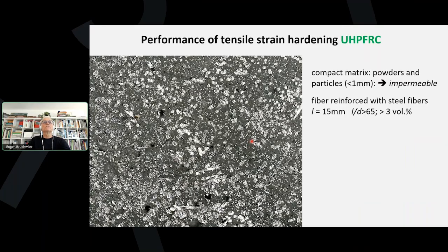Now let's look at the performance of so-called tensile strain hardening UHPFRC. As already mentioned, we have a very compact matrix. The powders and small particles are actually optimized such that all space is occupied by particles. In this way, we get the very compact and dense material. It is impermeable for water. Water cannot go inside it, in the material. And also chloride ions cannot go inside the material. And this is a main reason why this material can be, or is actually, very durable.